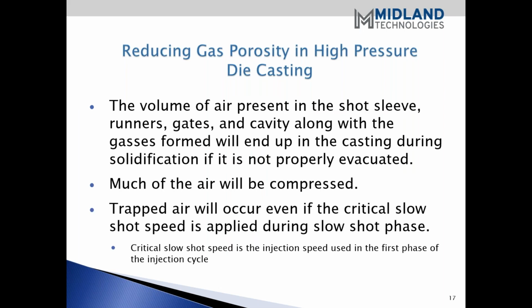Okay, so the volume of air present in the sleeve, the runners, the gate, and the cavity, along with those gases formed, will end up somewhere in the casting during solidification if the cavity is not properly evacuated. Much of the air will be compressed, and we know that because of the nature of high pressure die casting. We can do some things to increase the pressure on the metal, and that's what we're referring to in this case. Trapped air will occur even if the slow shot speed is applied during slow shot phase.